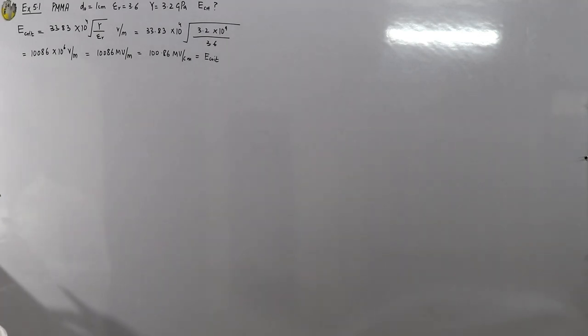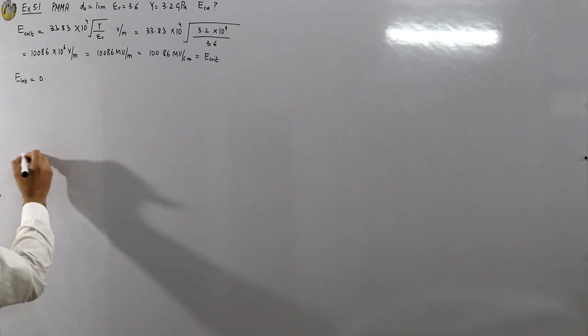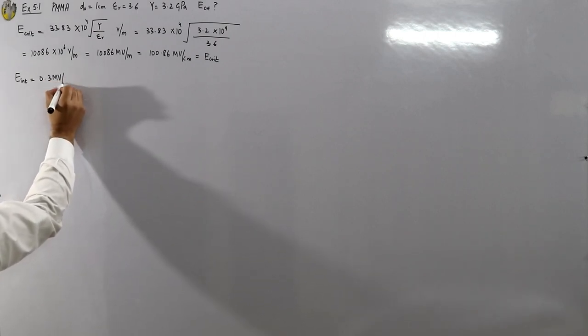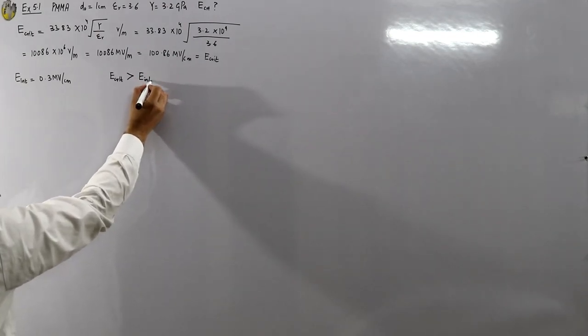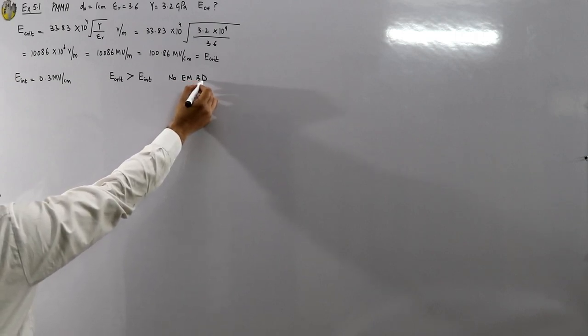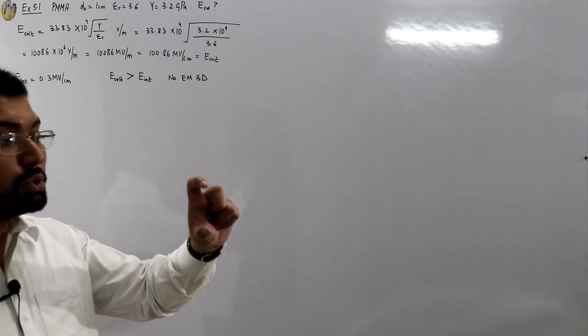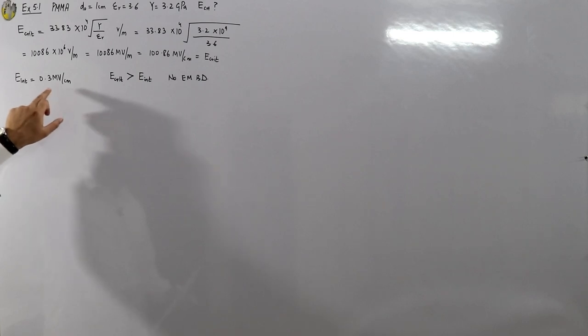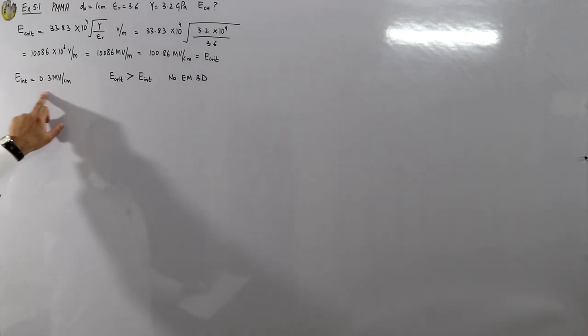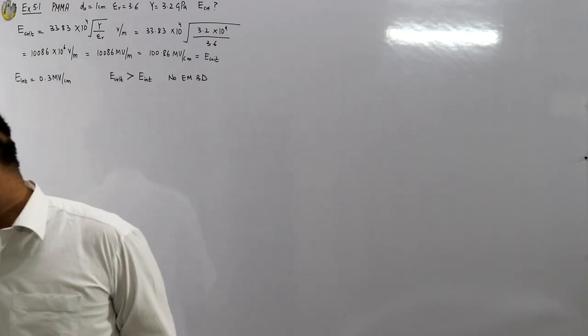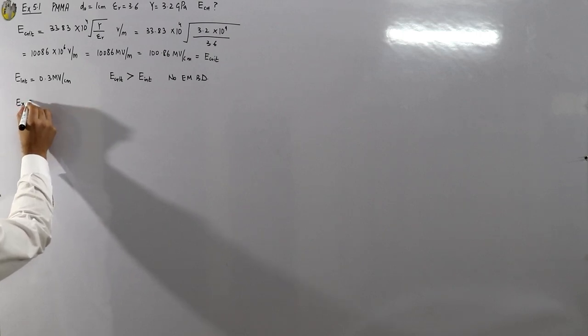The intrinsic breakdown field is 0.3 MV/cm. Since the critical electromechanical breakdown field (100.86 MV/cm) is much greater than the intrinsic value, there is no possibility of electromechanical breakdown — the intrinsic breakdown will occur first. PMMA is a stiff material, and compressing it to 60% of its original thickness requires an enormous field.